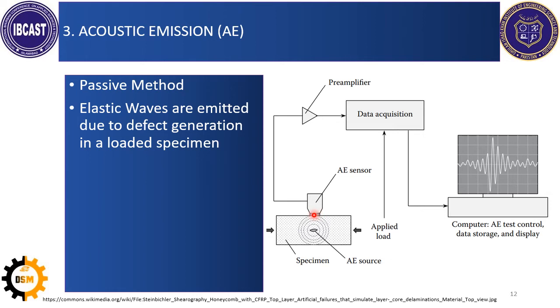If you see here, this is the acoustic emission sensor, and it is a contact-based acoustic emission sensor. But this system is very famous in structural health monitoring, that's why I put it here, and it can easily detect those elastic waves, amplify them, pre-process that data, and give you some graphs, and you can decide what is the size of that crack. So it also gives you monitoring. If you have a crack, initially there will be some elastic wave. After some time, if this crack is propagated, this elastic wave will change its trend, and you can see whether the crack is getting dangerous or not.